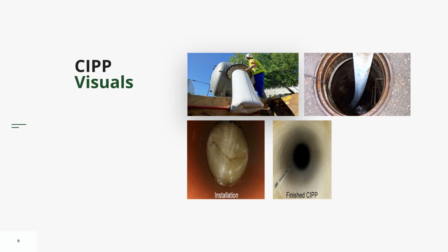Absolutely no excavation. You put it inside the pipe, you pressurize it to make it fit the host pipe, and then you cause the resins to kick and to go off and become hard. Then you cut off the ends, and then you can go in with robotic cutters and cut out your laterals. The photograph in the middle, lower with the red background, it says installation. That is the actual inversion process inside the host pipe. So the host pipe is red in that case, and this is inverting and moving along.